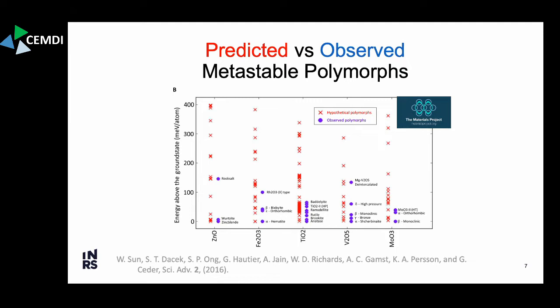So it might be stable, but it's not in its ground state. A purely metastable state is basically defined by all of these configurations that aren't in the real ground state structure. This is shown for a few different materials: zinc oxide, iron oxide, titanium dioxide, vanadate, and molybdenum oxide. And you can see the theoretically predicted polymorphs versus the observed polymorphs. And you can see that there's a whole lot more theoretically predicted polymorphs.